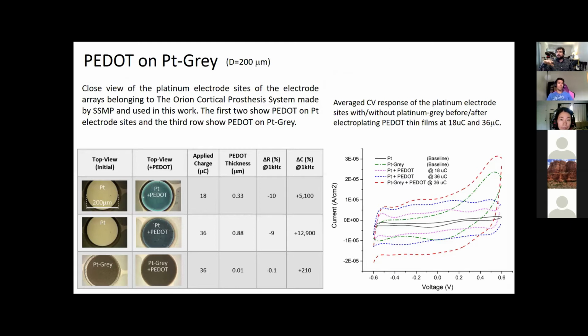So once you plate PEDOT on smooth platinum, they come off so easily after a few days under stimulation in PBS, or even using Scotch tape, you can easily peel them off. But then I ran a technique, also learned from Dr. Martin's group. He's famous in PEDOT research, and he recently came up with this adhesion promotion technique, which is chemical. So using diazonium salts that I also synthesized myself from his recipe.